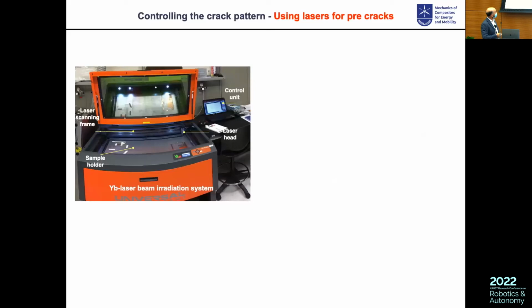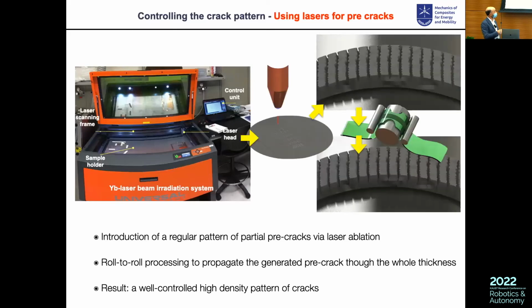What we are going to do now is that instead of cracking the film just by pulling on the film, you decide where the cracks are going to happen. So the way you do this is that you just make notches, right? You come with whatever you want, but something that is going to make an imprint. So you force the localization of your crack. Here, typically, we do it with a laser beam. So you come with a laser, and then you plot the initial position of your cracks, and then you are going to get crack propagation through the thickness at these different points. So you get a pattern of cracks that can be much more controlled and much more organized.